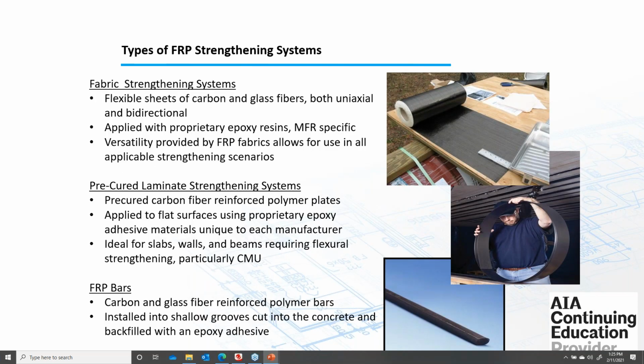So there's 3 different types of FRP systems: fabric, pre-cured laminates, and then FRP bars. So the fabric is what we're looking at in the picture on the top right there. You can see it comes in a roll. These are flexible sheets of either carbon or glass or the aramid fibers, the Kevlar as well. Then they come in uniaxial or bidirectional. There's also a quadriaxial fabric that we carry. I don't think we really sell it here in North America, but over in Europe, they use a lot of these quadriaxial materials for some of these really old, 14th century churches and castles, things like that, they're just trying to do what they can. But when we say uniaxial, the fibers run the length of the sheet. So there's that ruler on the picture in the top right.